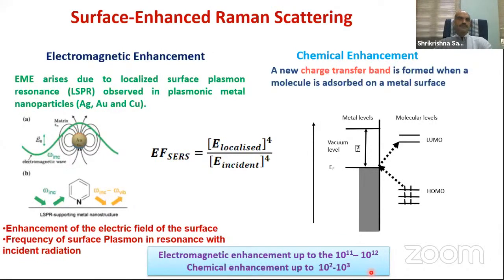Of course, there is another enhancement responsible for this: the interaction of the molecule with the metal surface, which is chemisorption. We know that there is physisorption and chemisorption. Whenever there is chemisorption, there is a charge transfer between the molecule and the metal surface, and this charge transfer is also responsible for enhancement in the Raman signal. However, this chemical enhancement is not too much, only of the order of 10² to 10³. Electromagnetic enhancement is huge, of the order of 10¹¹ to 10¹².